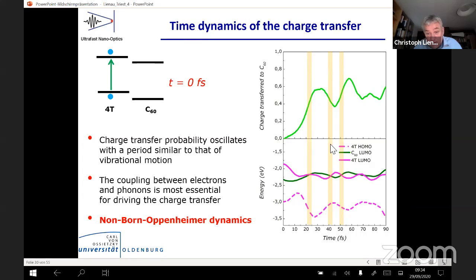There's also plotted the time evolution of the energy of this lowest unoccupied molecular orbital of the C60. That's the green curve. And you see at early times, directly after optical excitation, these are not in resonance, they're detuned. And as you know from coupled harmonic oscillators, two detuned harmonic oscillators cannot couple to each other. There's no efficient energy flow, and thus there's no charge transfer. The two are not in resonance.